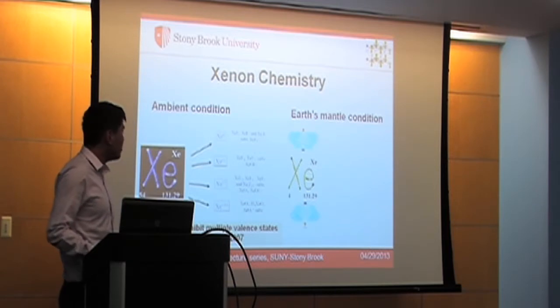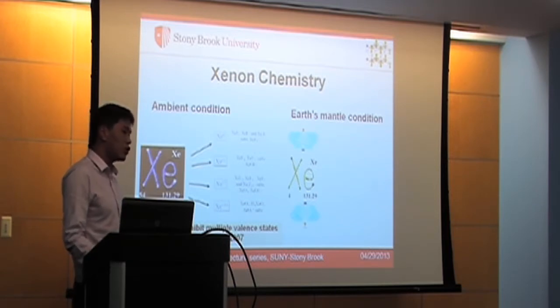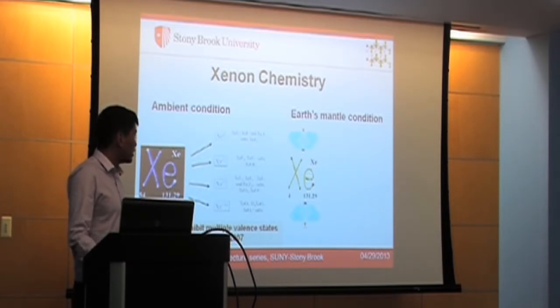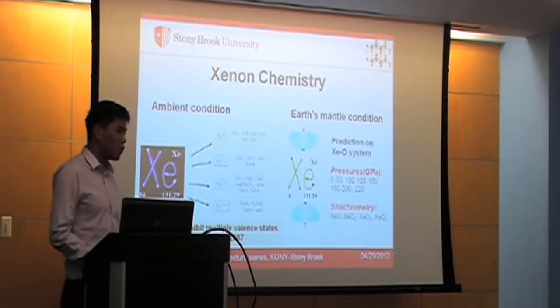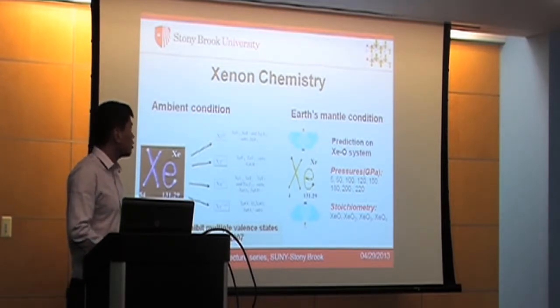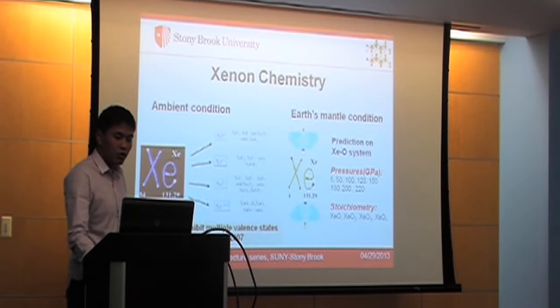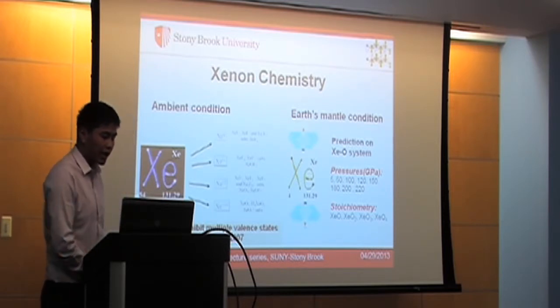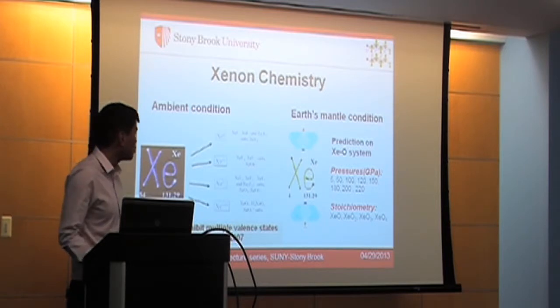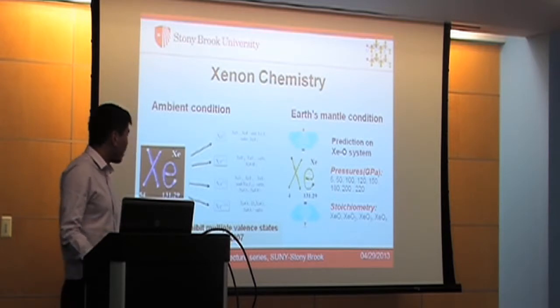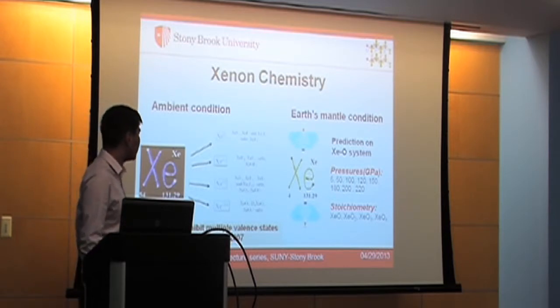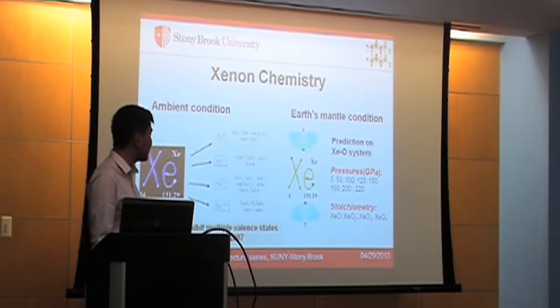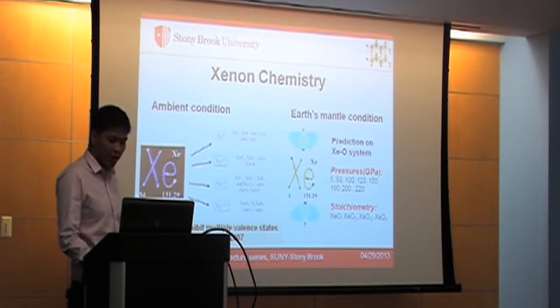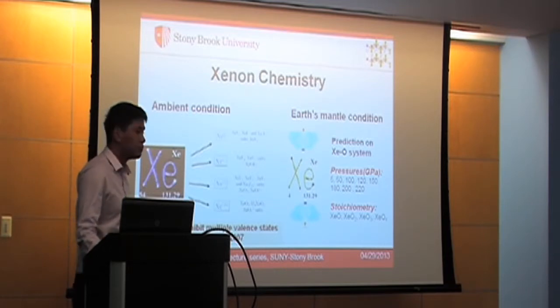So to confirm this, we can do either experiment or theoretical calculations. However, experiment requires very high cost. So here, theoretical calculation will play a major role. So we applied our method to predict the xenon oxide system at a wide range of pressures and some given chemical stoichiometries. As we know, we already found that xenon can form +2, +4, +6, and +8 valence states. So we studied the possible compounds XeO, XeO2, XeO3, and XeO4.